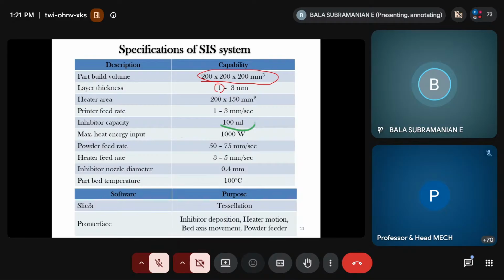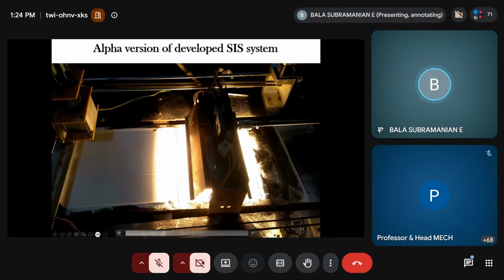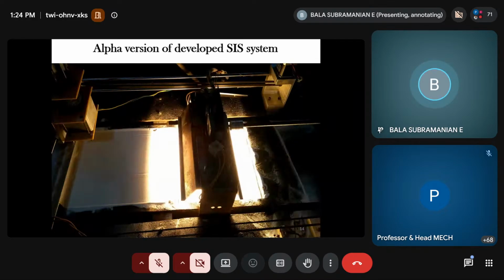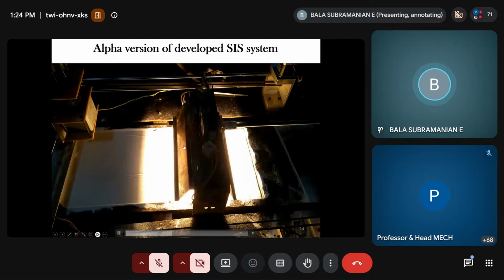You can see now the heater is not switched on. It is automatically switched on when it is reaching towards that particular region. Okay, unnecessarily we don't want to waste the energy and not to sinter the particles. So we are making the G codes in such a way that it is switching on according to the required place. So here also a simple linear screw and stepper motor arrangement to make the proper small, incremental motion and controlled motion. Okay, so that the uniform distribution of the heat, that is very, very important for sintering.